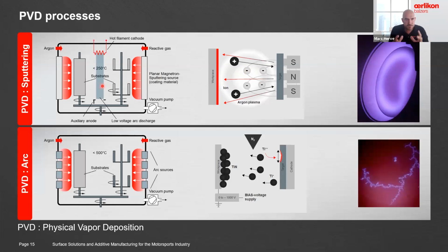Another technology which is very close is what we call the PVD Arc, where in this case, we will again have solid targets of the material we want to apply, and we're going to create an electrical arc on the surface. By doing this, we will have a very dense, very hard coating, but this process is made at much higher temperature, up to 500 degrees C.